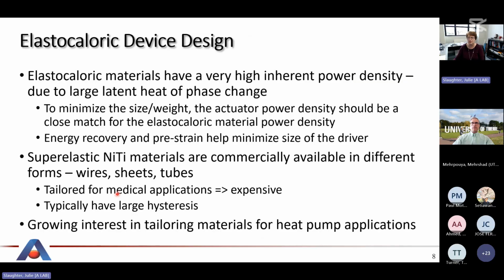So really, when you approach the device design, the materials inherently have a high power density. And so you really want the actuator power density to match that as best it can, so that you can minimize the size of the system. And then another important point is that energy recovery and pre-strain can help minimize the size of the driver. And what we mean by this is when one elastocaloric element is loading, another one is unloading, so you're recovering that mechanical energy.